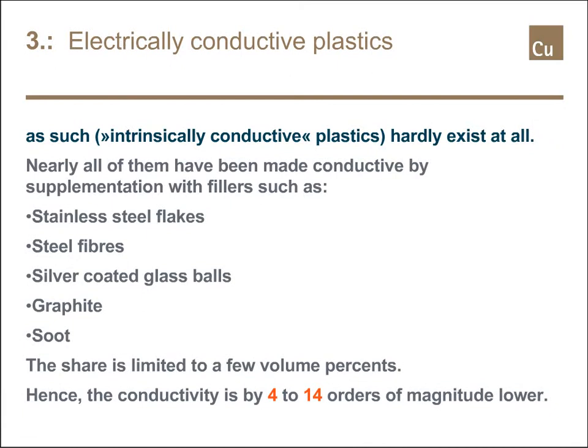The third one is electrically conductive plastics. Now, electrically conductive plastics as such, the so-called intrinsically conductive plastics, do not really exist, or hardly any of them at all. Nearly all of them are made conductive by supplements and additives, and with fillers such as stainless steel flakes or steel fibers, sometimes silver-coated glass balls are used, or graphite or soot, which is mixed into the plastic and therefore makes it a bit electrically conductive. The share is limited to a few volume percent because you want to use the properties of the plastic, not those of the conductive material, and hence the conductivity of these materials is between 4 and 14 orders of magnitude lower than those of metals.